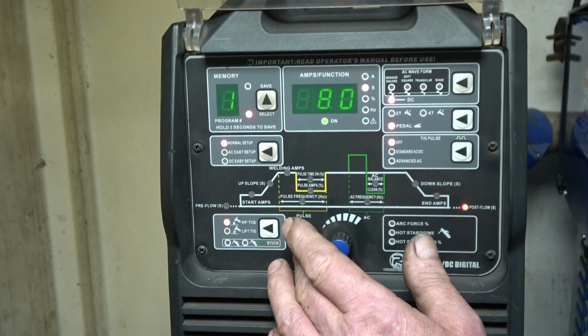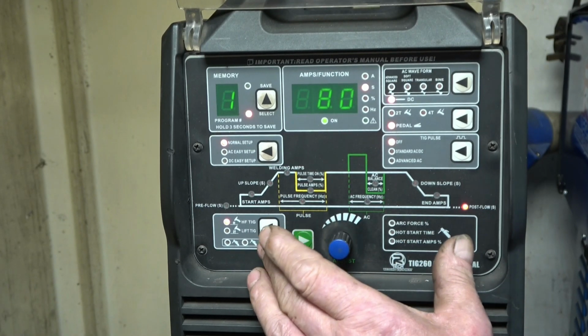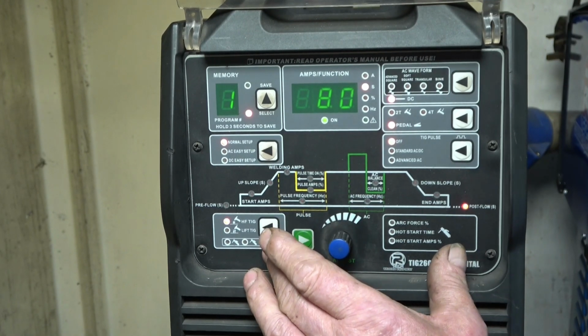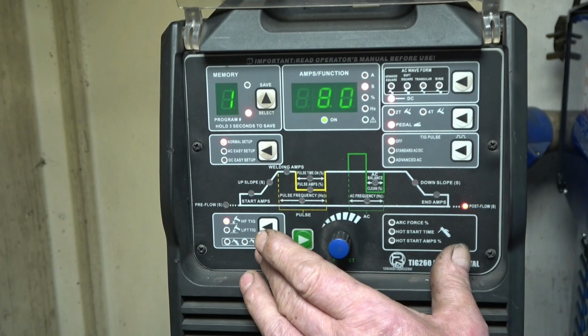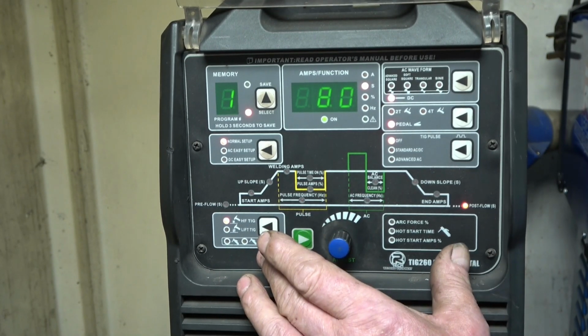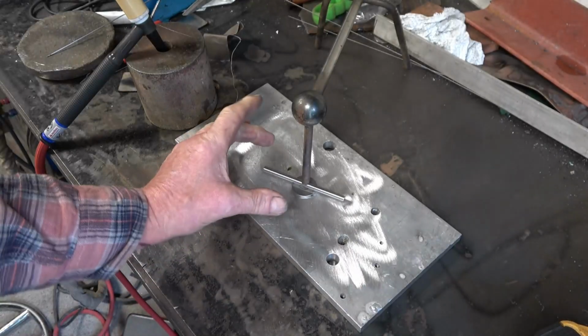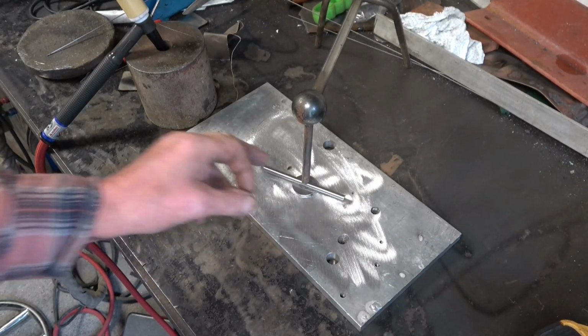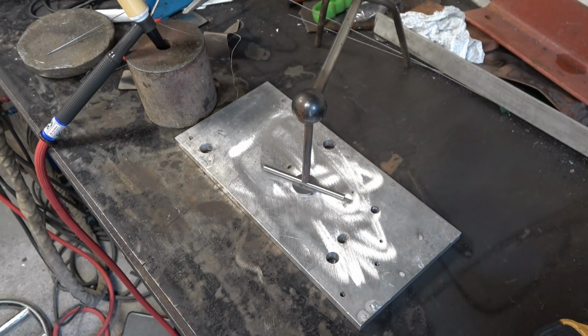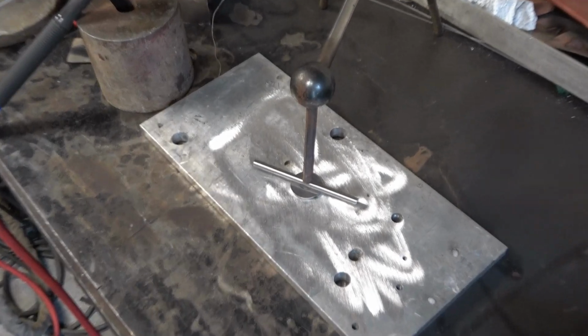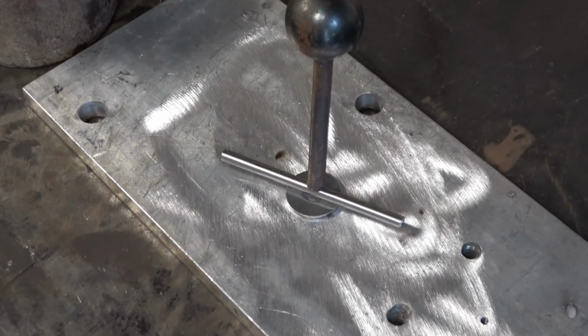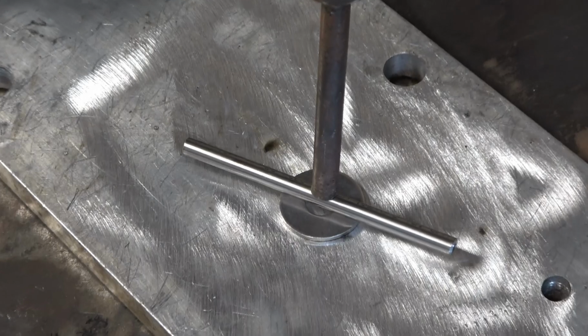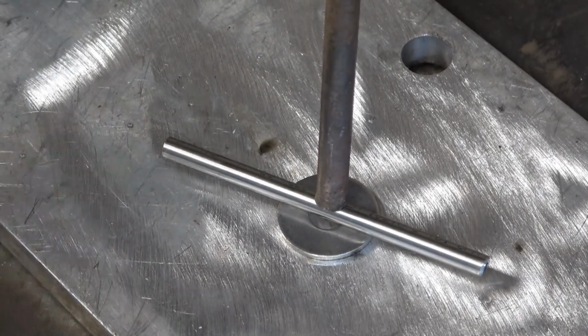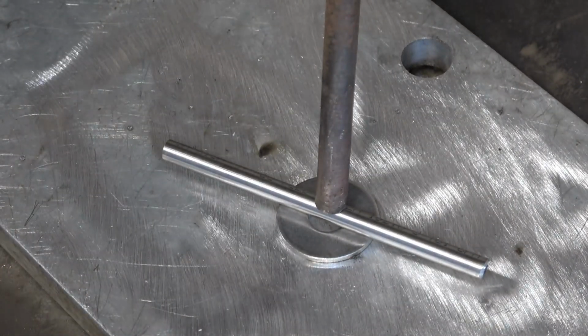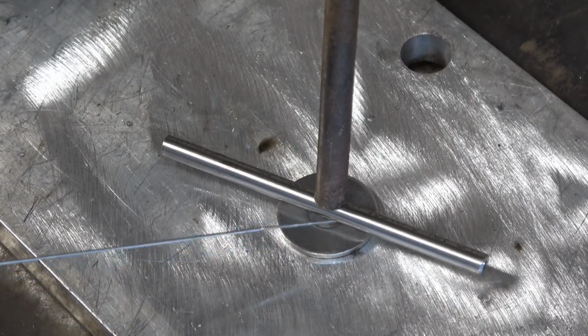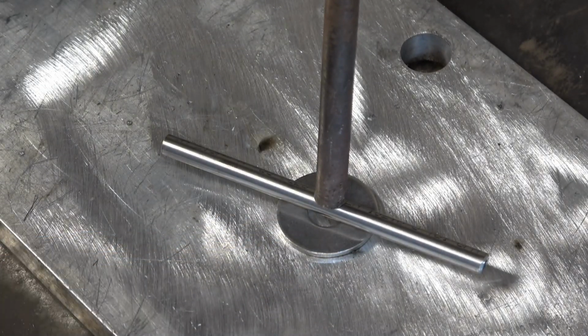Exactly the same, everything's low as it'll go. In the end flow, or post flow, I've got 8 seconds. That helps keep the weld clean and also helps to cool the tungsten. This is the job I've got to do. It's a stainless washer in some thin walled stainless tube, and he wants them welded together. I'm not quite sure what they're for, but I've got 20 to do, and all he wants is a nice little weld. One there, same on the other side.